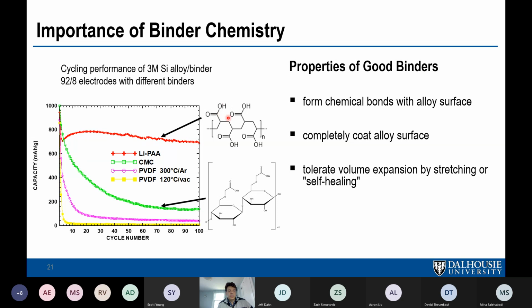And these carboxylic acid groups can form direct bonds with the surface of silicon, which is typically covered with hydroxide, so hydroxyl groups. And so this can react with a hydroxyl group and form an ester bond with the silicon surface. So essentially, binders that can form chemical bonds directly to the surface of the alloy and also completely cover the alloy surface tend to cycle well. Polymers that don't form bonds, like PVDF, and don't coat the alloy surface, typically don't cycle very well.